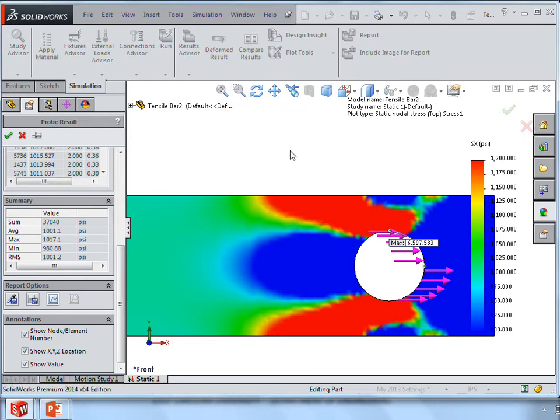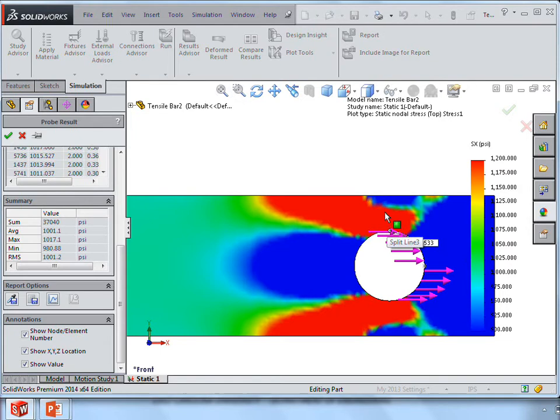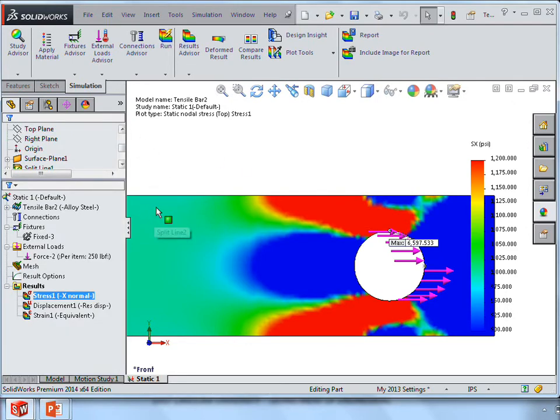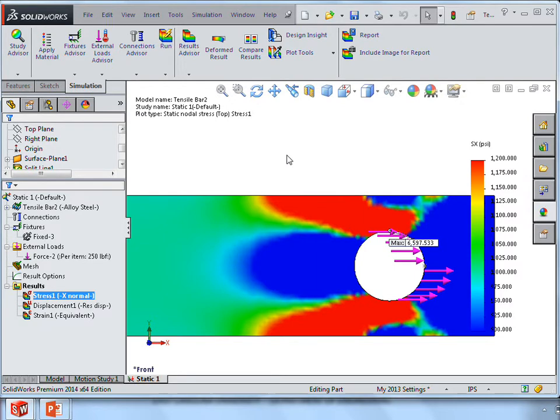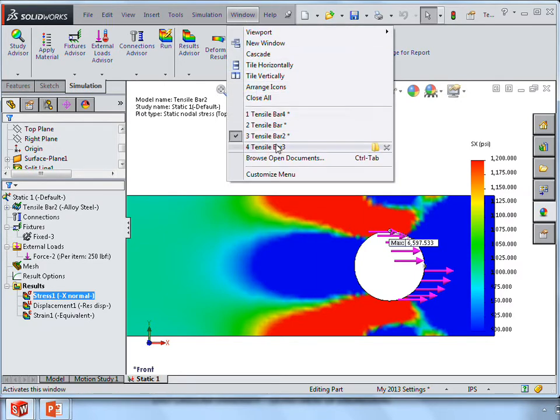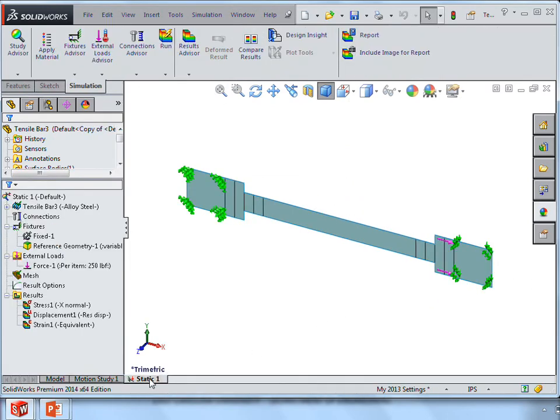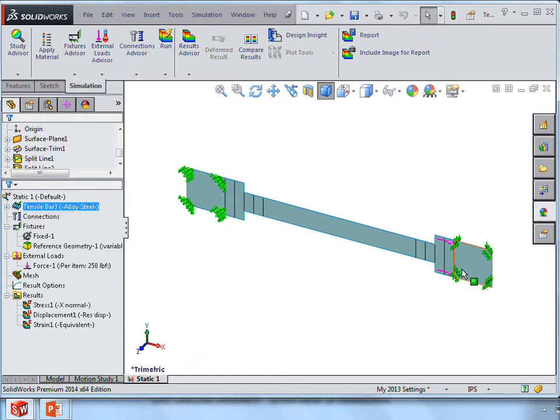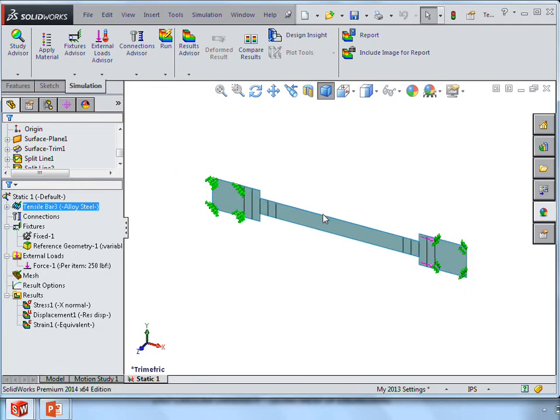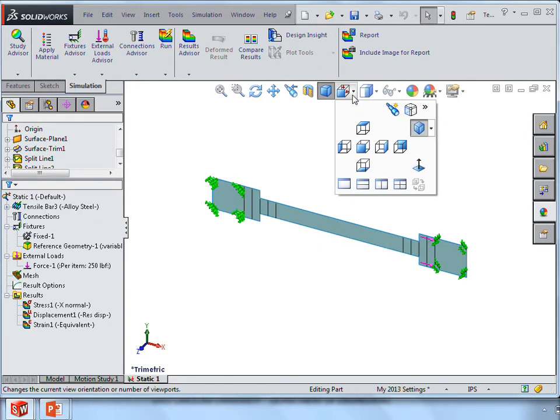Now, in either one of these cases, though, if we were trying to determine the strength of whatever material we were testing, we would see that we would be failing this where the maximum stress occurs, which is going to be around where it is gripped. Of course, to get a good value of strength, I want this to fail down in the zone away from all of these localized high stresses. So one way of doing that would be to thin out the bar toward the middle. So we're going back to our gripped configuration here. And we've fixed this end, fixed this end but allow it to move in the x direction and apply the 250 pounds. Now in the middle, I've cut the width in half, so half an inch. So our nominal stress will be 2,000 psi, so we should fail out in this region.